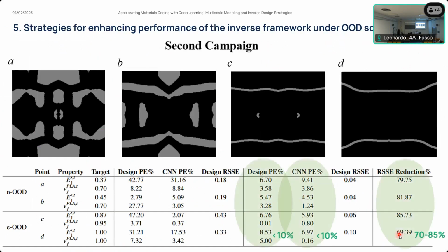If we present the data for the 4 critical points that we picked, which were the ones associated with the largest error during the second optimization campaign, we obtained very good results, both for the framework and even for the predictor itself. All of the errors associated to these 4 designs are below 10% error, with an extensive exploration of the latent space, but it still could be even larger, so possibly these results can be even improved. And a large reduction of the error compared to the first optimization campaign.